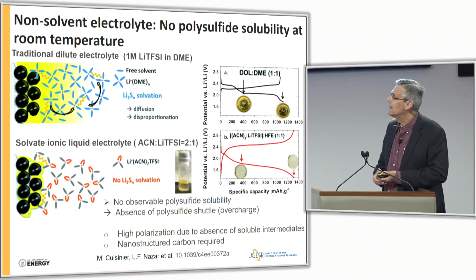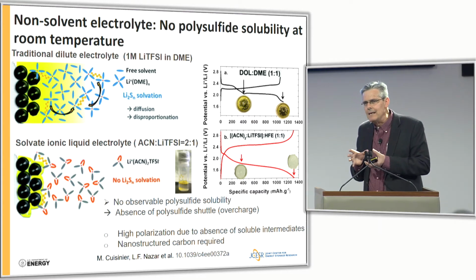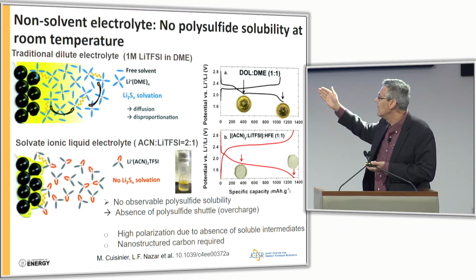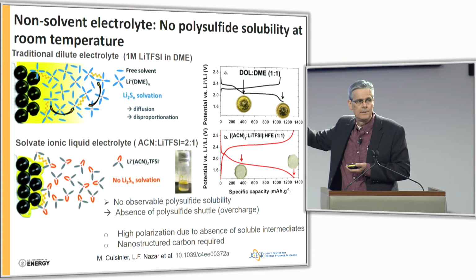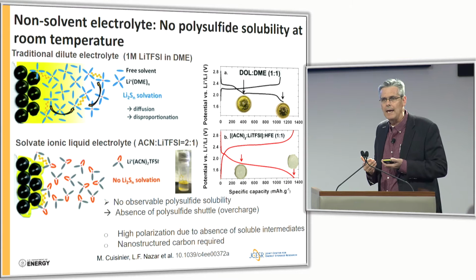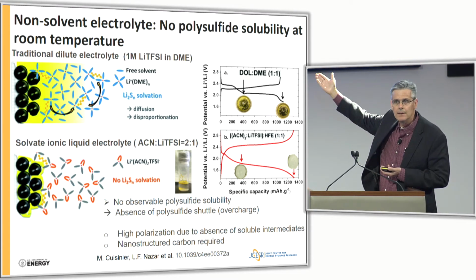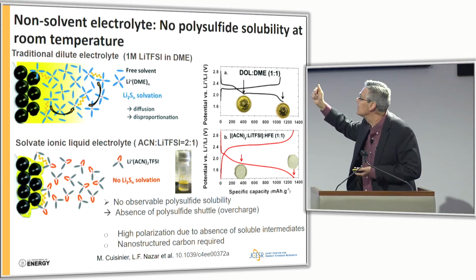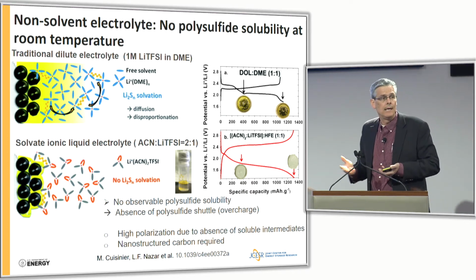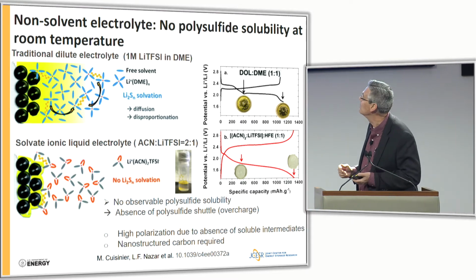All right, so this idea that I'm going to describe to you turns on its head the idea of a non-solvating system. So we've all read the literature, you're familiar with Watanabe's work, you're familiar with Linda Nazar's work, and this idea of using what was referred to at the time as a non-solvating electrolyte. So it's that exact same acetonitrile in a 2-to-1 molar relationship with salt, and a hydrofluoroether added. The acronym is TTE. This is a pseudo-symmetric tetrafluoroethyl tetrafluoropropyl ether.